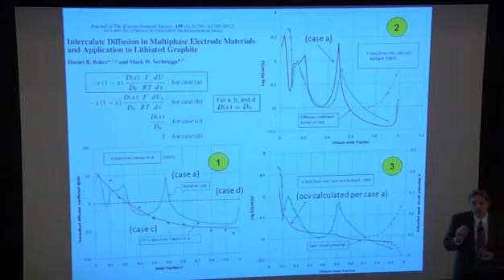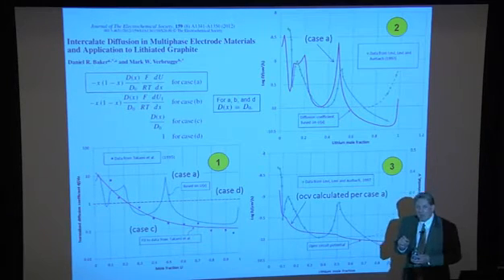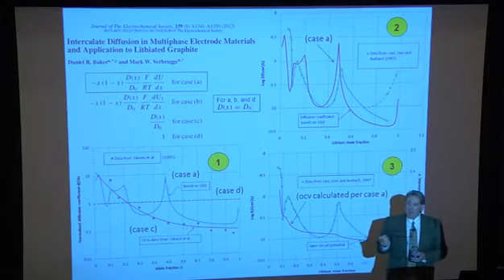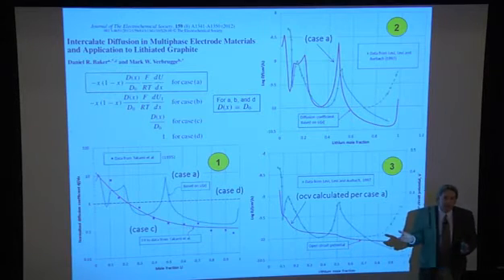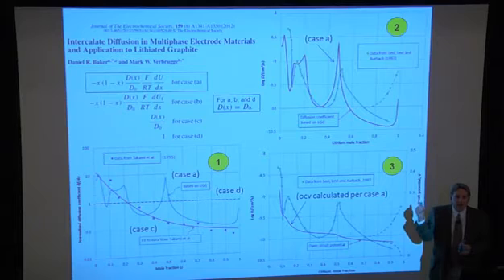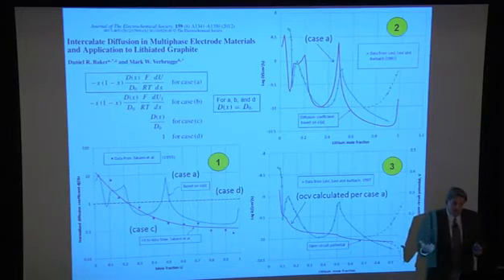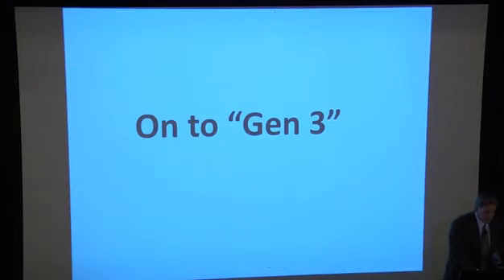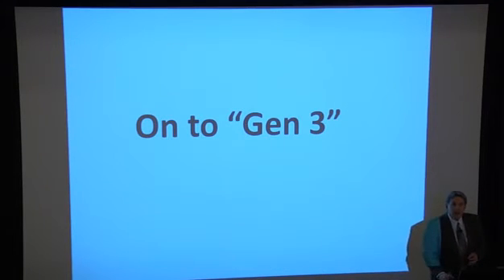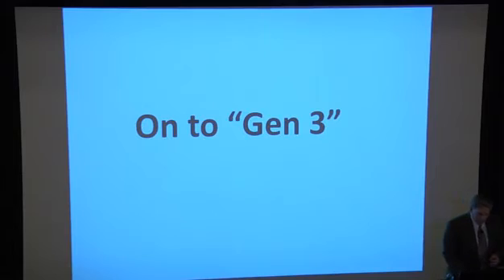So my point is, we were very fortuitous in that counter-life modeling. We had parameters in there that we were juggling to try to make it fit the data. It looked like it fit the data pretty well, but obviously transporting these multi-phase materials, or transporting graphite, is a lot more complicated than a dilute solution treatment. So with that, I'm going to go on now to Gen 3 systems.